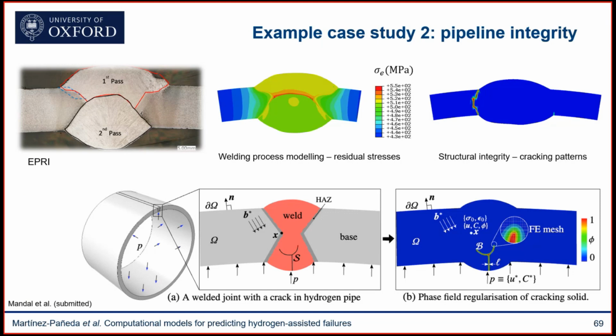Ideally, of course, we want to transport pure hydrogen, and we want to do that at very high pressures. And as I said, this is very complicated to determine experimentally because it's very difficult to capture the conditions in the heat affected zone. We cannot produce standard compact tension samples from the heat affected zone. So the welds are too complex to test experimentally, one could argue. The other aspect is that you also have residual stresses, of course, so it's quite a complicated process to test experimentally.